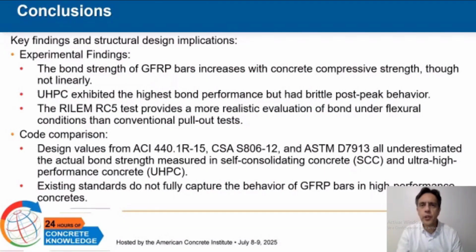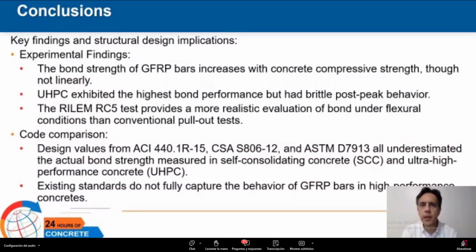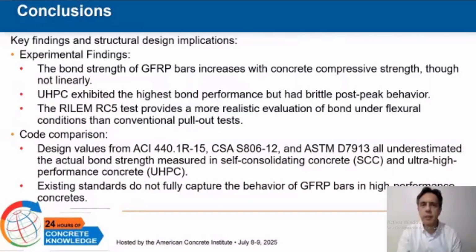In conclusion, the results of this study demonstrate that the bond behavior of GFRP is significantly impacted by the concrete matrix, particularly its compressive strength and internal structure. Although UHPC offers superior bond strength, it also exhibits brittle debonding behavior that must be considered in the design process. The RILEM RC5 test method proved valuable for simulating realistic stress conditions, producing bond values that exceeded those predicted by ACI, CSA, and ASTM pull-out-based provisions.